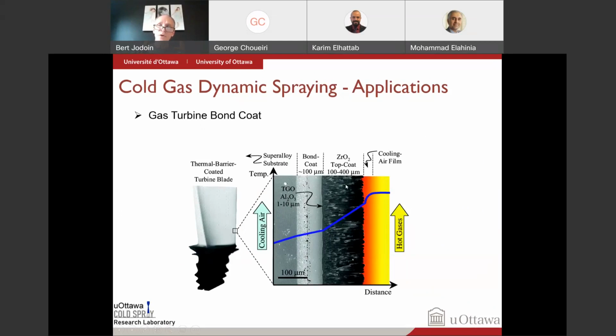So what you do is you apply a ceramic coating right there. The problem with the ceramic coating that you apply on your base material is they don't match in thermal expansion coefficient. So it's going to delaminate. So what we do is we apply an intermediate coating called a bond coat, which does have a thermal expansion coefficient in the middle between the base material and the ceramic top coat that you're applying as an insulator.